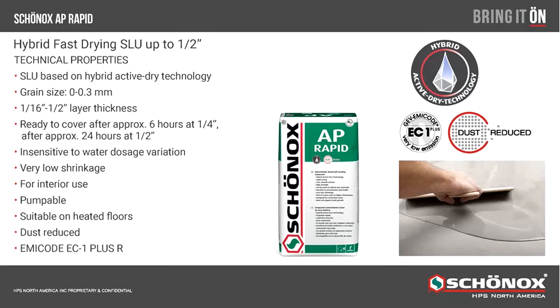So your AP Rapid is active dry, again, 1/16 to basically 1/2 inch in one lift. So this is our traditional 1/2 inch self-leveling compound, ready for floor covering in about 6 hours at 1/4 of an inch. If we go to a full 1/2 inch, normally around 24 hours, ready for placement. We're insensitive to our water dosage. Again, it's not as critical with water as it would be with some of our other self-leveling compounds. A little extra water in these mixes will not degrade the system because it's actually taking that free water that it needs for the hydration process.